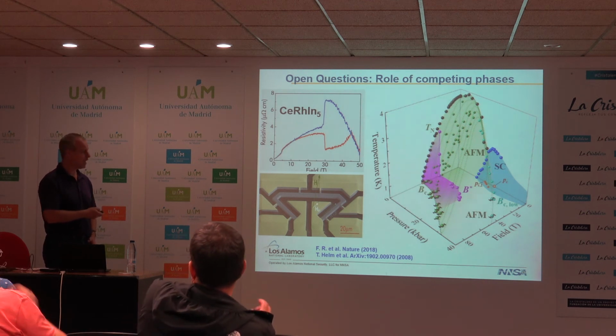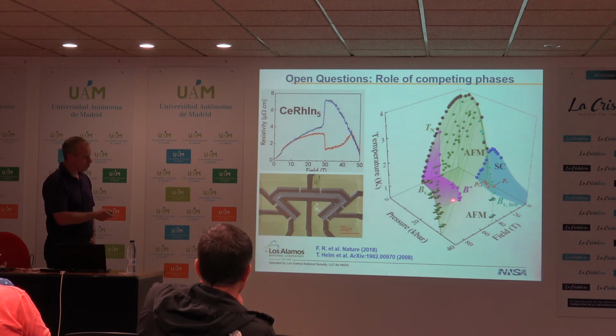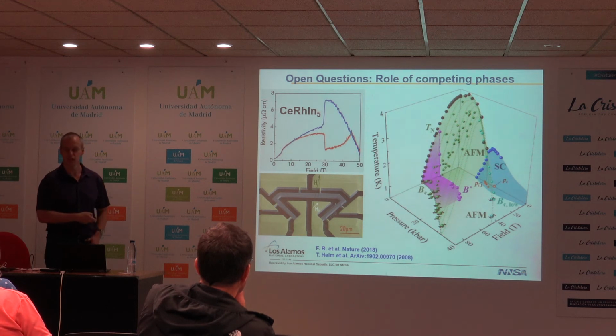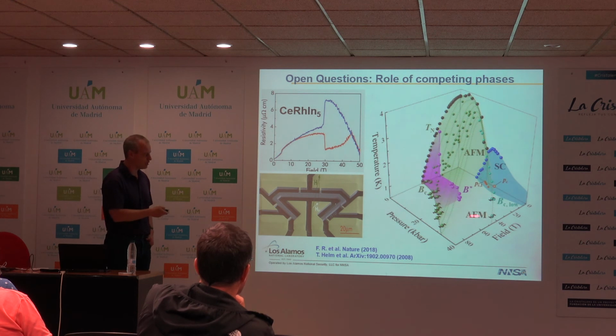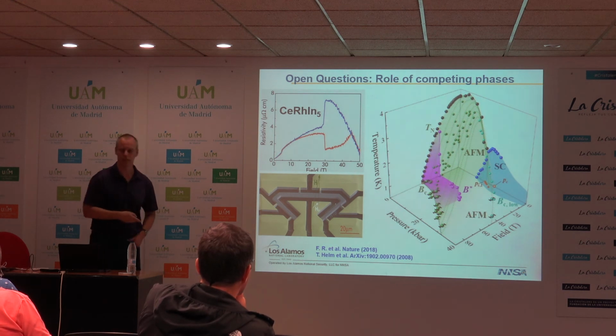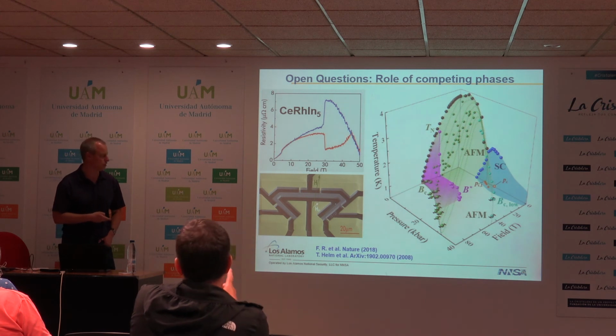And so perhaps this change of the electronic structure from small to large is also quenching this nematic-like response. It's possible that they're tied, but it's also difficult to make that direct comparison because we're now in fields of 30, 40 Tesla. It's not obvious that the pressure scale that is changing the exchange interactions in zero field should be equivalent, and that you should necessarily just draw straight lines here. In fact, at even higher fields, we see evidence for a re-entrant magnetic state when you're sitting at large pressures and large magnetic fields. This still needs to be investigated, but there's an anomaly in the resistivity that looks like the antiferromagnetism maybe lives to even higher pressures than originally thought.